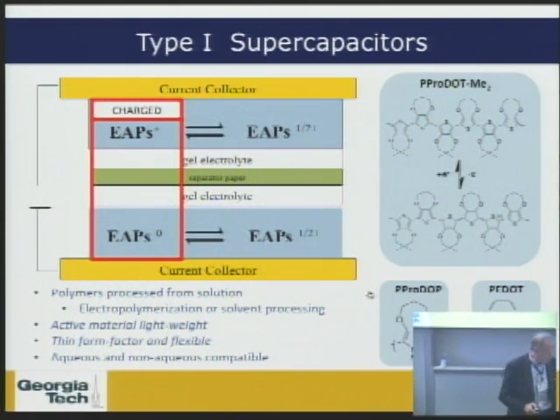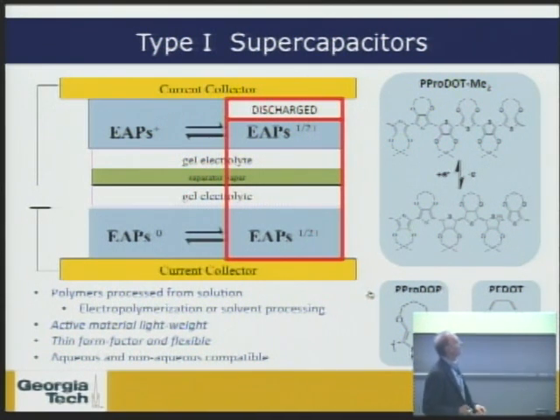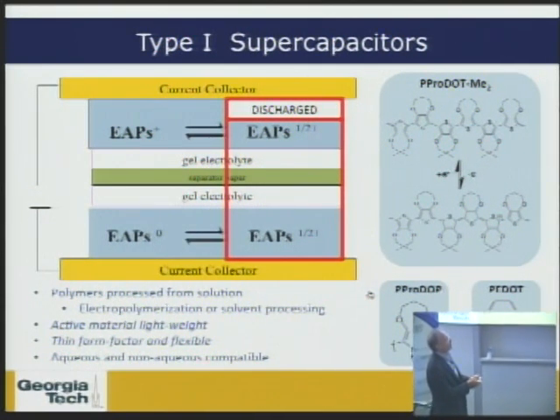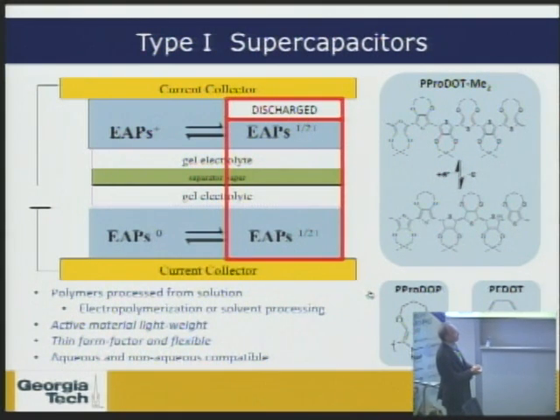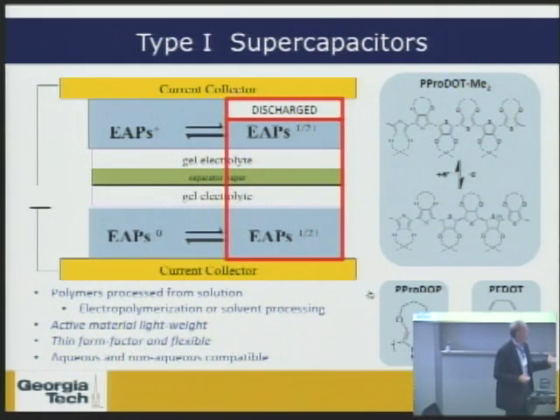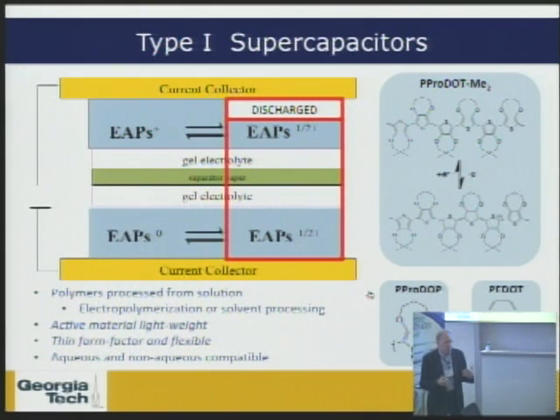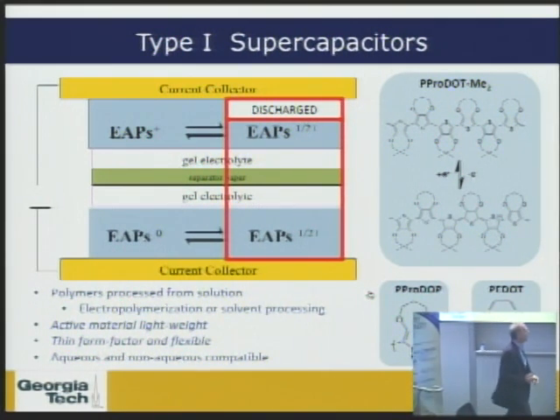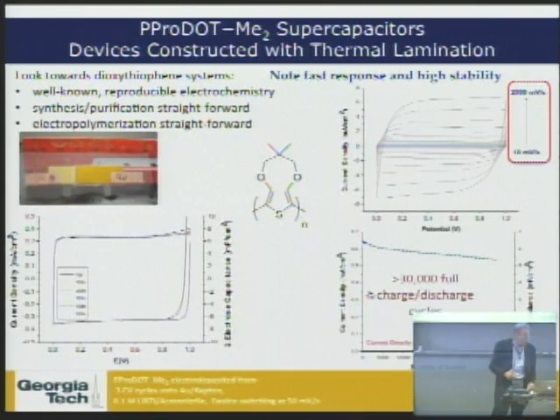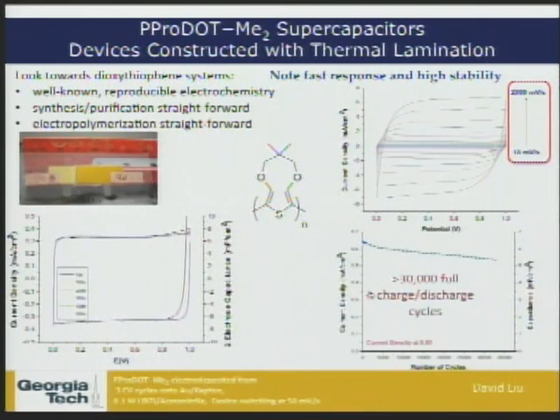And now if we, in essence, short the system, if we allow the system to come to electrochemical equilibrium, then we are discharging our cell. And we can go back and forth between charging and discharging, and this is in essence how a battery would work, or more specifically for how these work as a supercapacitor type of a material. And so again, I'm going to be talking about how the form factor of polymer films on flexible electrodes can make this potentially useful. What you're looking at here is a photograph of a laminated